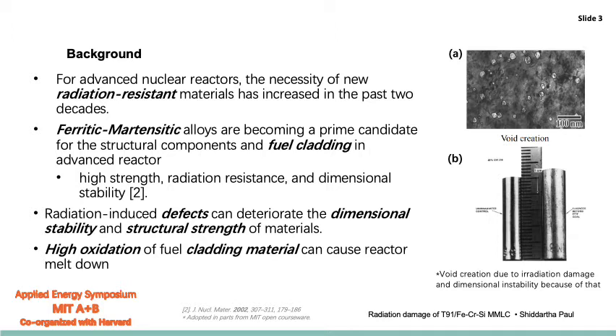Conventional zirconium alloy has a very high oxidation tendency and has been used for decades in nuclear fuel cladding application. That can lead the reactor to produce a vast amount of hydrogen, and that hydrogen can be trapped in the reactor chamber, and at very extreme conditions like loss of coolant condition in the reactor, it can act as a hydrogen bomb and can produce a devastating accident like the one that happened in Fukushima back in 2011. Also, the radiation induced defects can deteriorate the dimensional stability and the structural strength of the material. So that's why we have also studied the defect formation behavior for those particular T91 iron, chromium, silicon MMLCs.